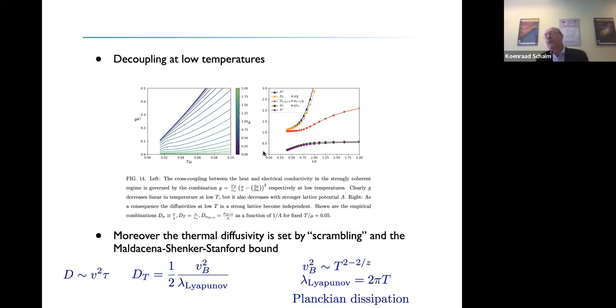And then the beautiful part of the story is that the thermal diffusivity in this system, not the charge diffusivity, because that's now completely independent, the thermal diffusivity in the system is precisely set by the scrambling velocity and the Lyapunov exponent that saturates the Maldacena-Shenker-Stanford bound in this system. And this is, of course, what is true Planckian dissipation in this system. In this particular system, you have a Lyapunov rate, which is 2 pi T. That's the real Planckian dissipation rate in the system that shows up in this diffusion constant.